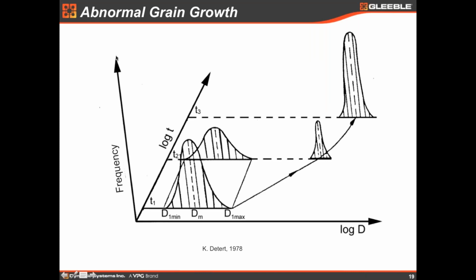As a frequency analysis here, we have the time and the grain diameter. So we start from a normal distribution of grain sizes. This is after you have a partial dissolution of precipitates, we have this bimodal distribution of grain sizes where you have the normal grains here and you have very big grains here. This is the abnormal grains. At the end of the process, we have only abnormal grains. So this is a disaster for mechanical properties, right?